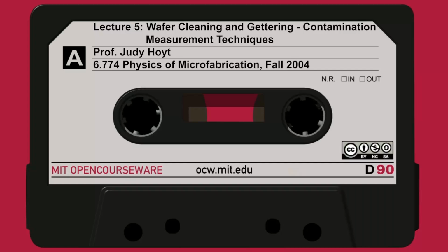This isn't a problem when you're thicker, but when you get down to this regime, for example below about 30 angstroms, you can have direct tunneling right through from the gate electrode into the channel. This constitutes a gate current, and the whole idea of CMOS is that there's no current through the gate insulator. That's not true anymore. There is current flowing through these gate insulators because they're so thin. This is a diagram I took from an older paper.